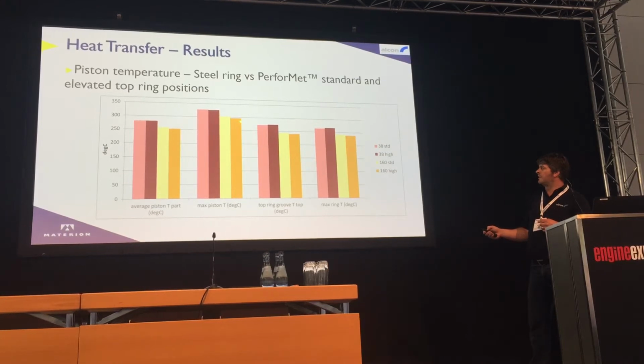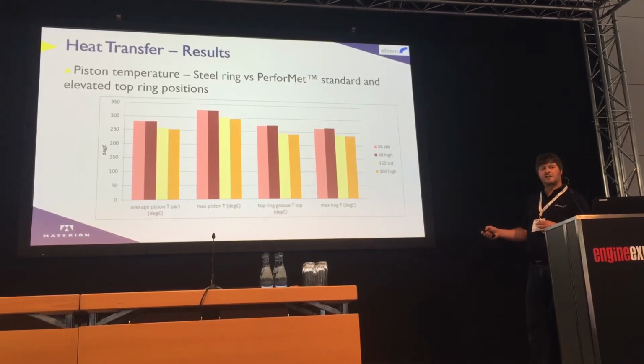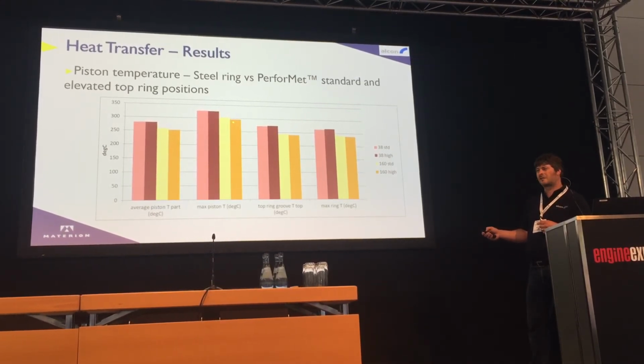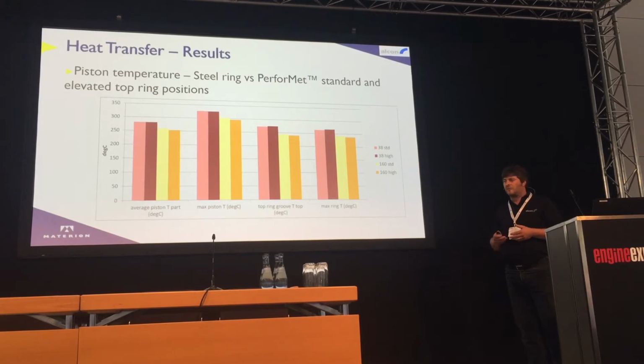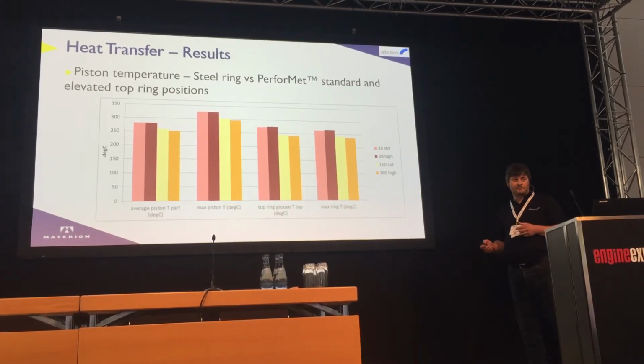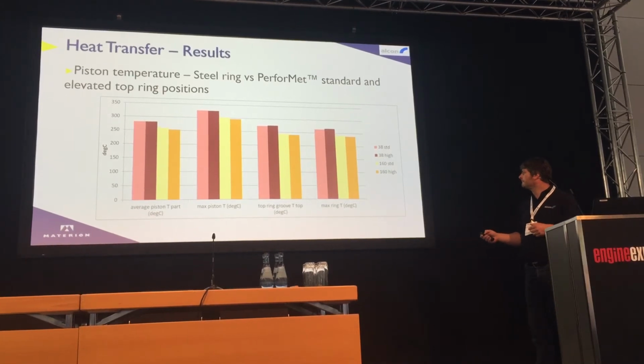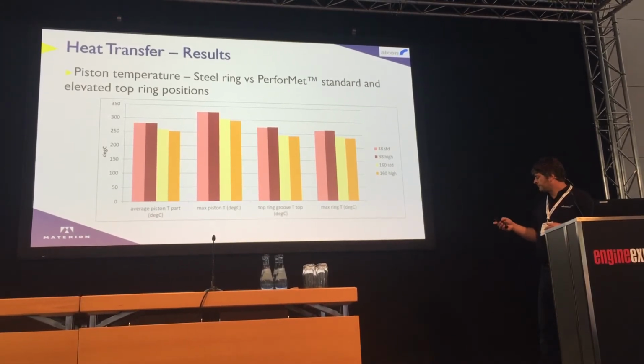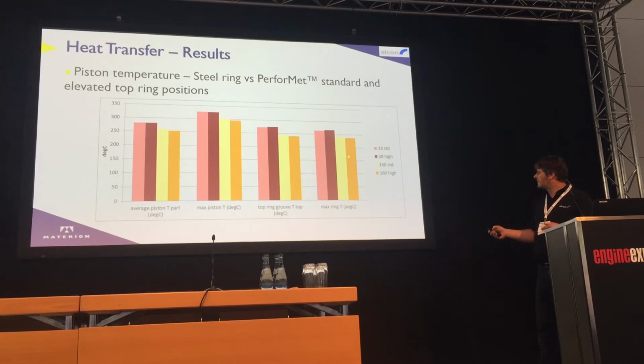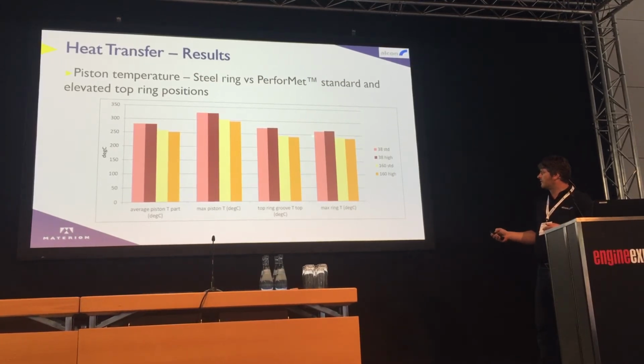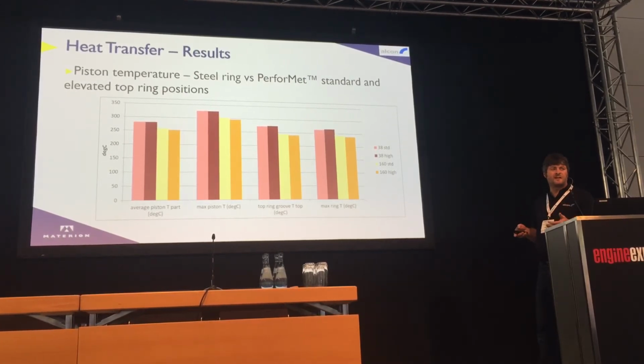And by moving the piston ring higher up the bore, we reduced it to just under 300, so 295 degrees C, which again is a significant number. So what that allows us to do is reduce the mass of the piston further to achieve the same fatigue life. And likewise, the actual top ring groove temperature gets cooler as well, so we can move the top ring up even higher.